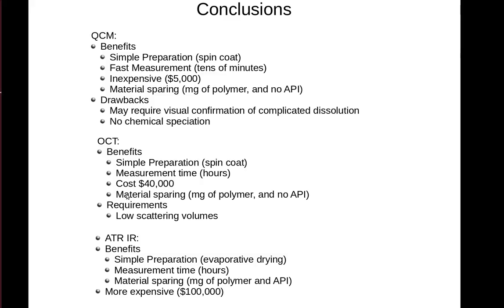And for the requirement of the polymer film itself, it has to be relatively low scattering. So these enteric, reverse enteric type coatings are fine. However, things with iron oxide or titanium dioxide probably are not as viable given the high scattering.